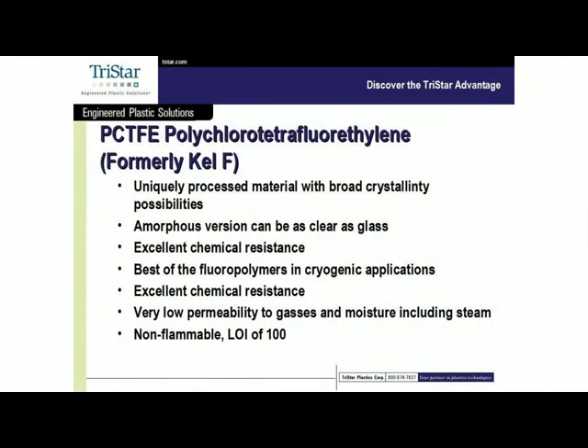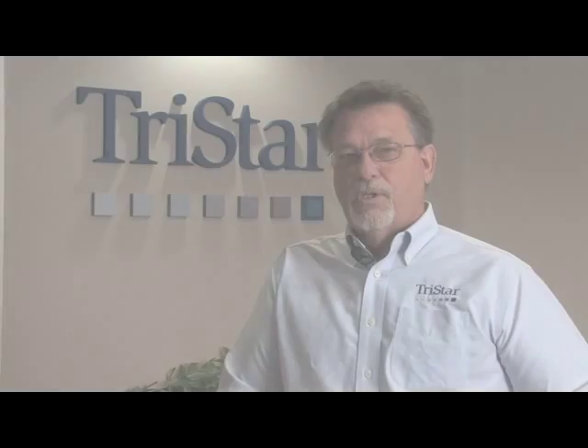Low permeability to gas. That's kind of a given with most of the melt processables, but CTFE or PCTFE has the best in terms of permeability. And that also includes moisture. And by moisture, I mean both saturation and also steam. It is one of the better materials in direct steam exposure. And then finally, it's non-flammable, as are most of the fluoropolymers, but in this case, the interesting thing is that the limiting oxygen index is 100, which is very, very good for a polymer.